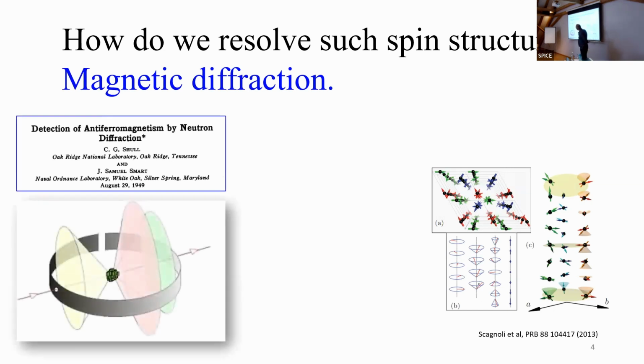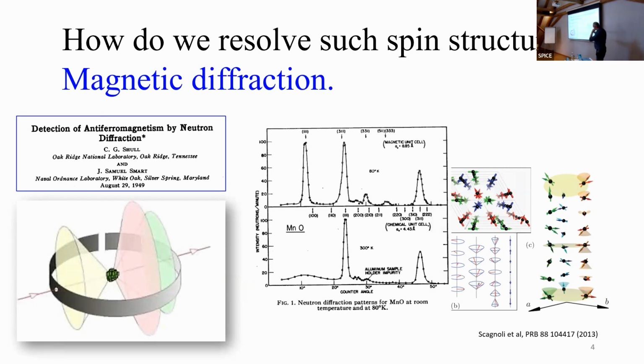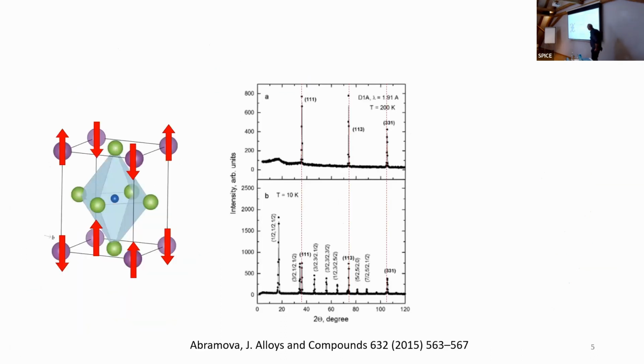This is one of the first papers from 1949 of a neutron diffraction experiment on an antiferromagnet, where the concept is very simple. You have this kind of beam of neutrons going through a crystal. In this case, it's a polycrystalline sample. That's important. We have our detector here, which is sort of a strip, and we have these powder rings that imprint on that, and we get something that looks like this. What you see here is the counter angle, and you have two panels, one above and one below the magnetic phase transition, where you see these regular structural peaks at room temperature, and additional peaks form when you go below the Néel temperature.